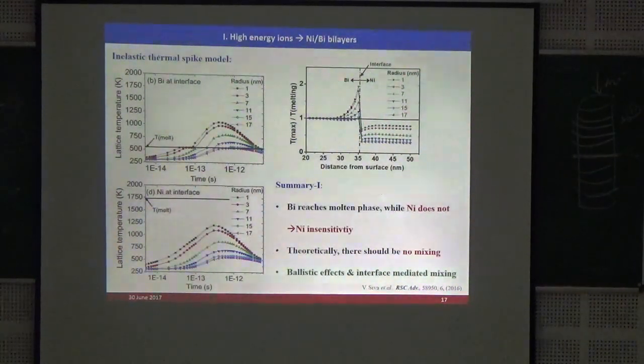If you see both of them together, we have plotted the maximum temperature generated during ion matter interaction over the melting point of each layer as a function of distance from the surface. So here you can see at the interface of nickel and bismuth, if this ratio is more than 1, that means the material is in molten phase. If it is less than 1, that means the material is not in the molten phase. Here you can see it is more than 1 in the case of bismuth, so that means bismuth is reaching molten phase, whereas nickel does not.